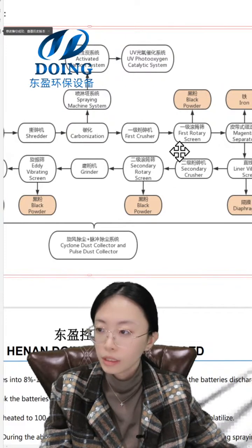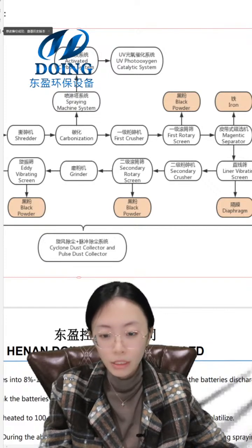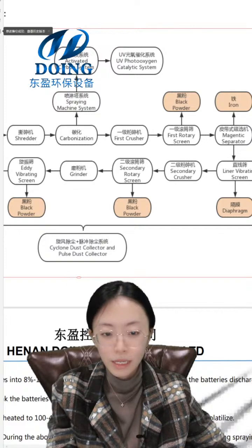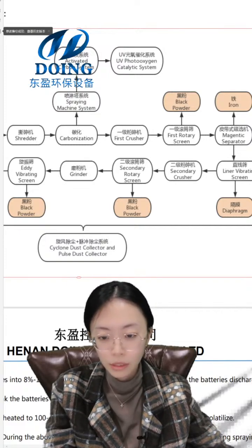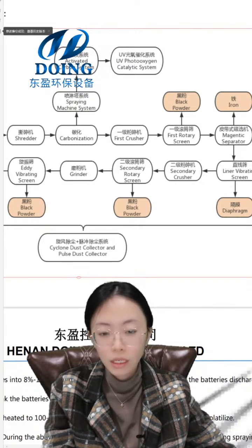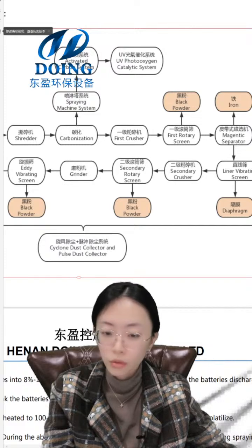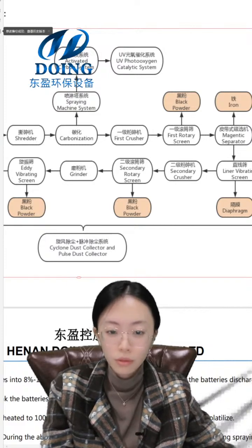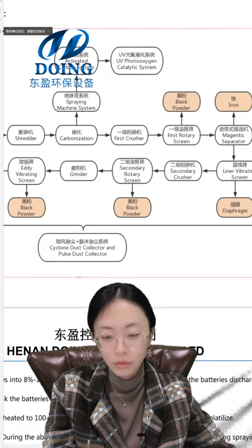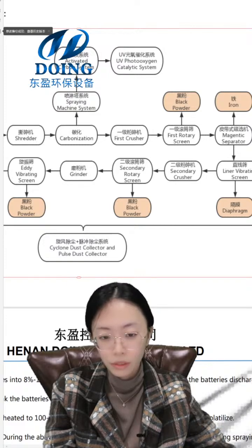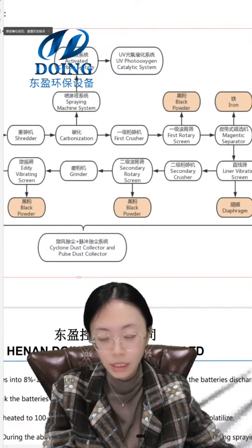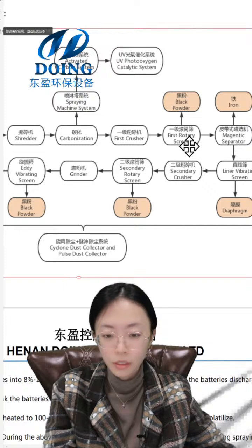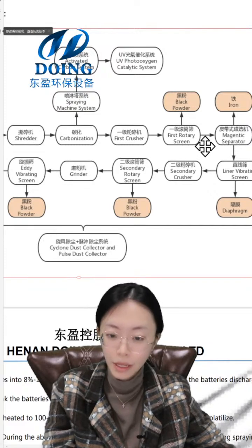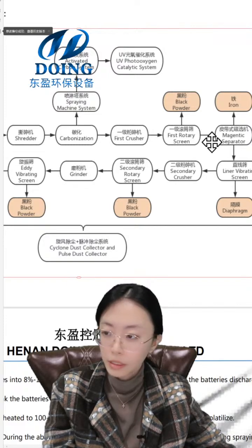And then it comes to the first rotary screen. The crushed material from the primary crusher is sent through the air transportation system, a sealed transportation system, to the fully sealed rotary screen for screening. Through the 120 mesh screen surface of the rolling rotary screen, the qualified raw material, like the battery powder, or what we call the black powder, will be discharged through the screen holes. And the black powder recovery rate in this step is nearly 60 to 70%. This is the first separation to separate the black powder. The length is 6 meters.